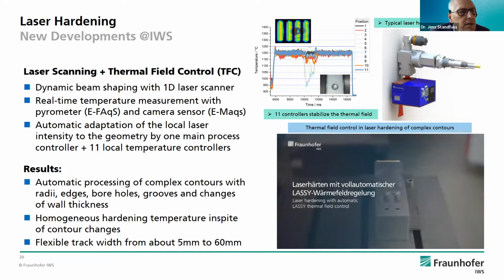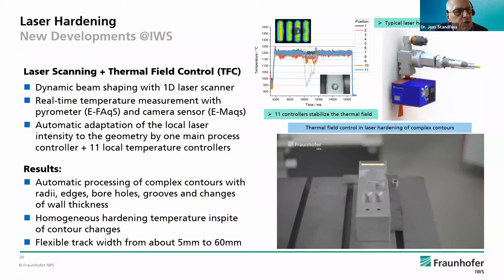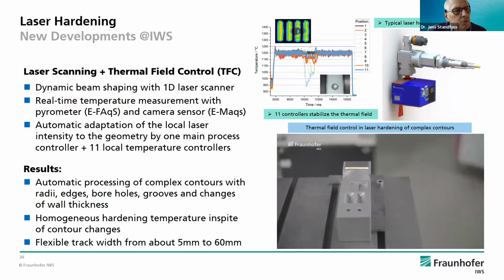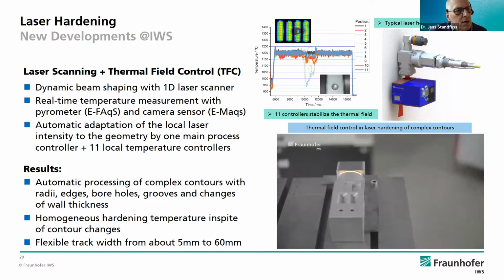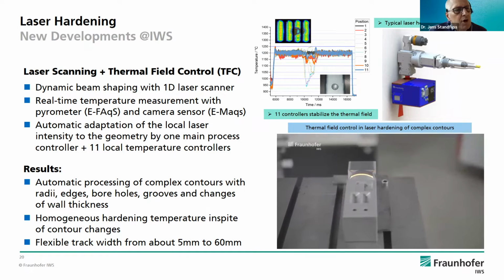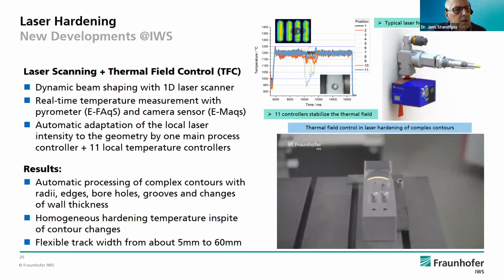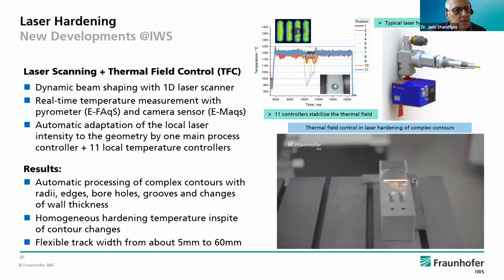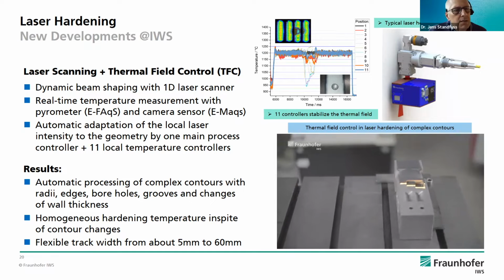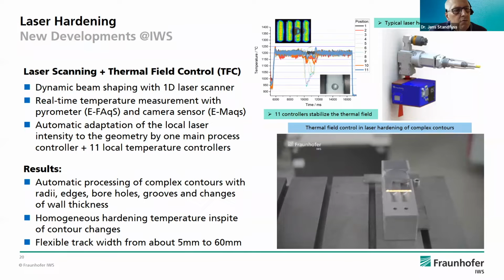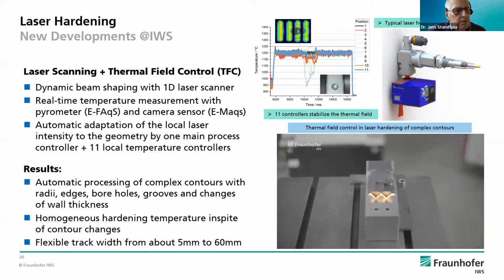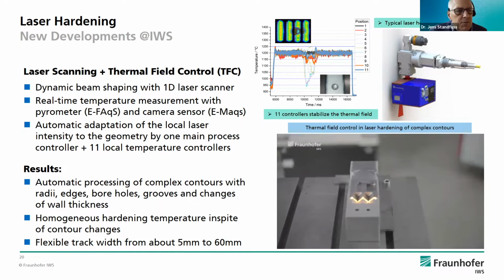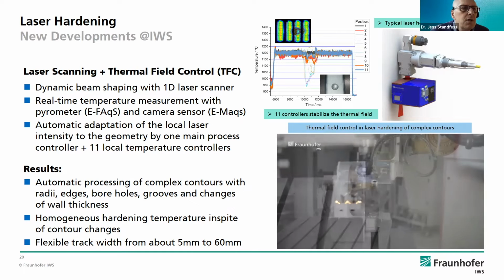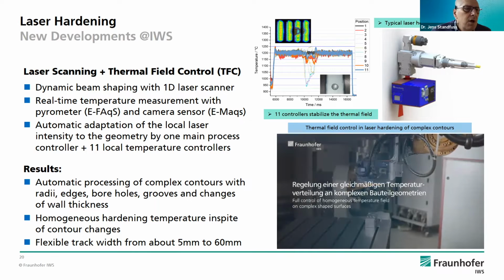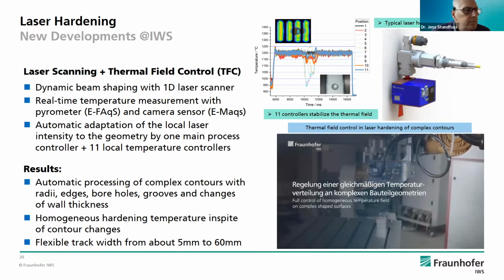And showing here in the part, you see it's quite a wide range of change of geometry, and the process runs automatically. You have a track up to 60 millimeter wide for hardening, adapting the process parameters by scanning laser power and also the scanner parameters automatically to the surface composition. And this without programming. You program only, based on some experience, on some values, the hardening depth to the material, and the geometry changes will be controlled automatically. And this is a very wide range of geometry. So it's a very flexible tool, at least the beamforming unit and also the temperature control system, to harden complex shapes.